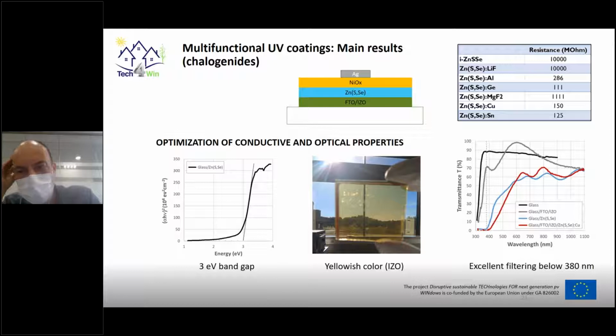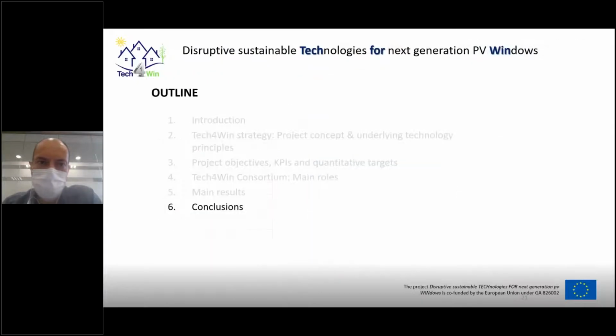This allows us to obtain layers with very good ultraviolet filtering, filtering almost all radiation below 380 nanometers wavelength. An important issue for making the solar cells is to dope in a suitable way both the P and N type zinc sulfoselenide layers, trying to make a homojunction. In the case of P type, we are working essentially with lithium, but most interesting is the N type, where we have a very good reduction of resistance using germanium, copper, or tin. So these are essentially the results achieved at this moment.